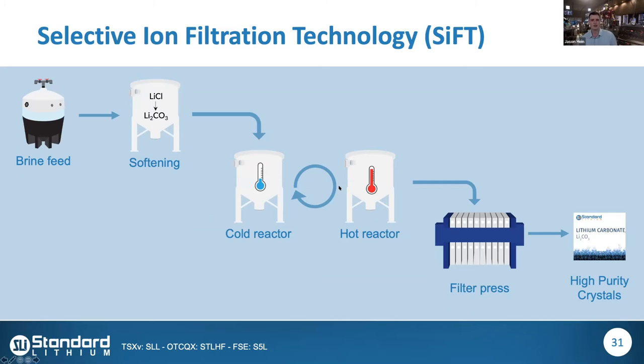An interesting thing about lithium carbonate is that it actually has an inverse solubility. At high temperature, it crystallizes, unlike most materials, which would dissolve at those higher temperatures. So by controlling the process like this, you can bring a lithium carbonate solution as a slurry or an impure material into this cold reactor, and carry out this dynamic circulation process where the crystals are generated under a controlled environment in our hot reactor, which are then isolated by the filter press.